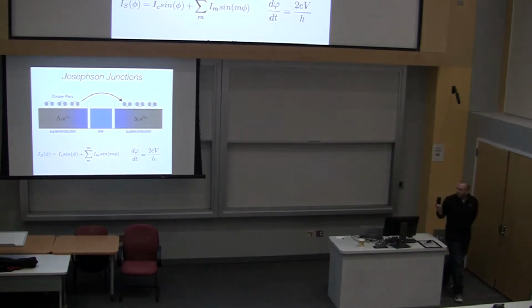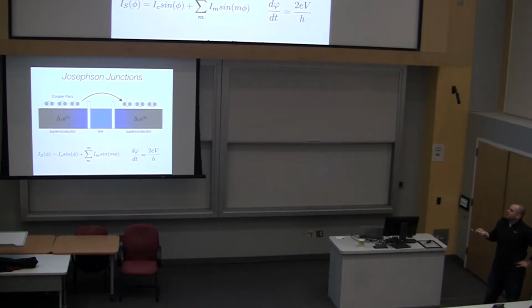So like I said, we now have a normal conducting region. This normal conducting region mediates the transfer of Cooper pairs between, say, the left and right lead. One thing that this does do is it modifies this current phase relationship. You might remember, I had J on the other slide, but it was just J equals sine phi. But when you start to make these interfaces clean and the material much better, like Javad does, there's a whole host of higher harmonic terms that become very important in determining the relationship between the current and phase.